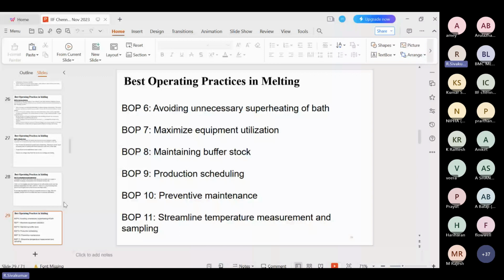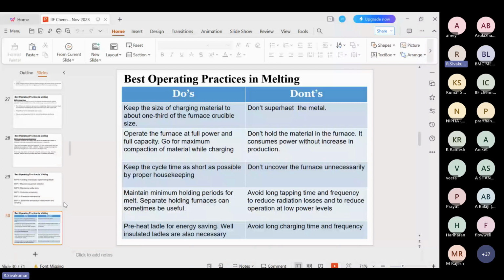So, best operating practices in melting: the do's and don'ts. Keep the size of the charge material to about 1/3 of the furnace crucible, and do not superheat the metal. Operate the furnace at full power and full capacity. Go for maximum compaction of material while charging, and do not hold the material in the furnace. It consumes power without increasing the production. Keep the cycle time as short as possible by proper housekeeping, and do not uncover the furnace unnecessarily.